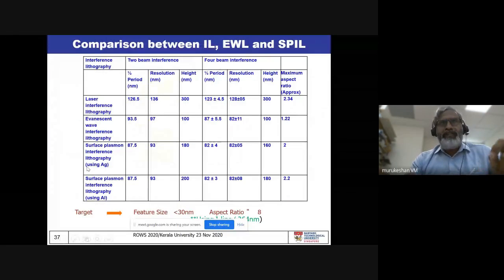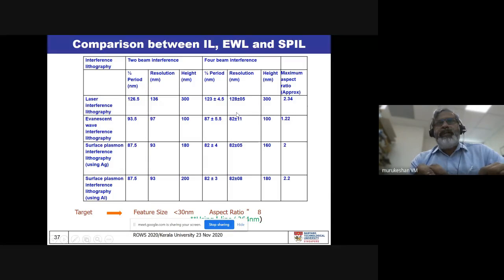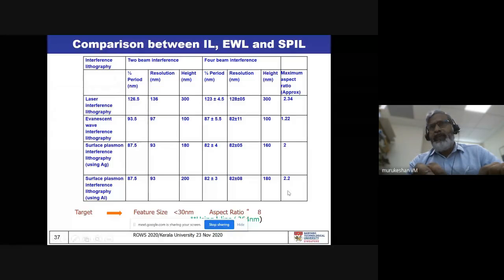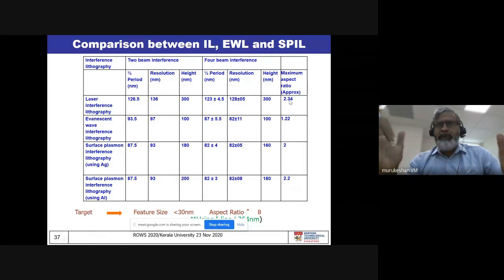So you see that if you do a comparison, with conventional laser interference lithography, you are able to get a resolution of about 128, 130 nanometer with an aspect ratio of 2.3. And when you use these near field concepts, from the evanescent wave regime to the surface plasmon regime, you are able to get not only the feature size reduced to 80 plus nanometer, but also an aspect ratio close to this value, about 2.3.